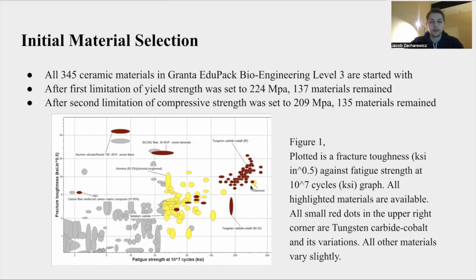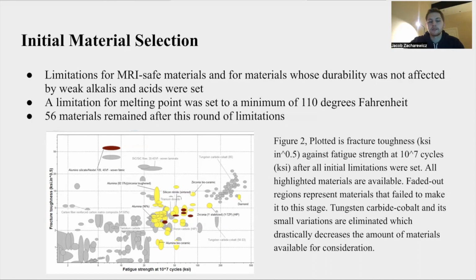All of these on the right-hand side are tungsten carbide cobalt, and they have different limitations. And we have expensive materials such as diamond and sapphire in this as well, and alumina and zirconia are very prevalent in this graph here. I then set limitations on MRI safe materials, materials whose durability was not affected by weak alkalis or weak acids, and a melting point minimum of 110 degrees Fahrenheit. And after all these limitations were put into place, I was left with 56 materials.